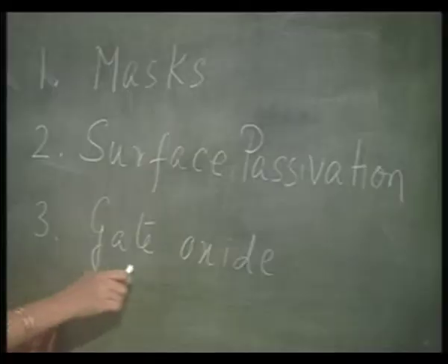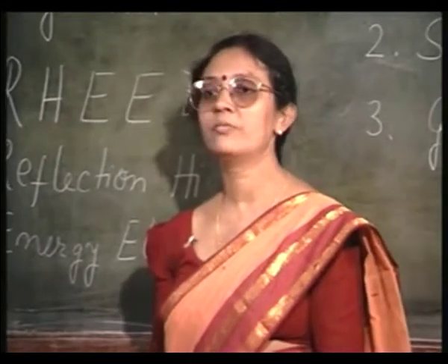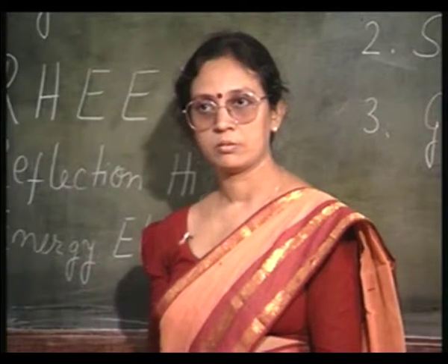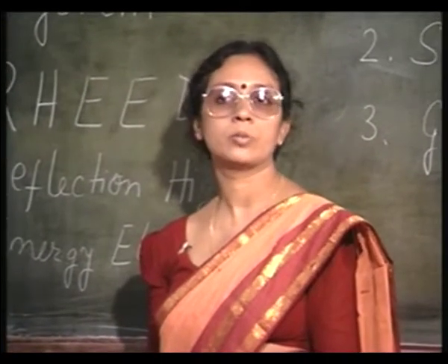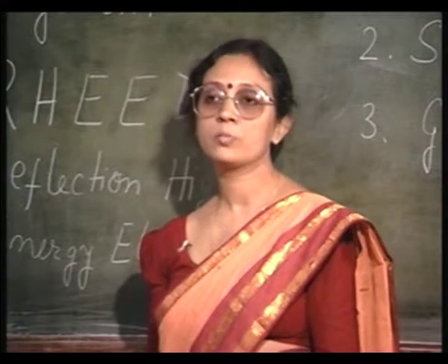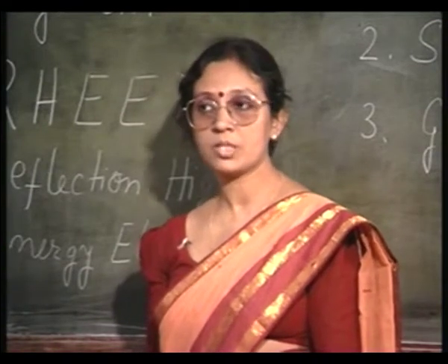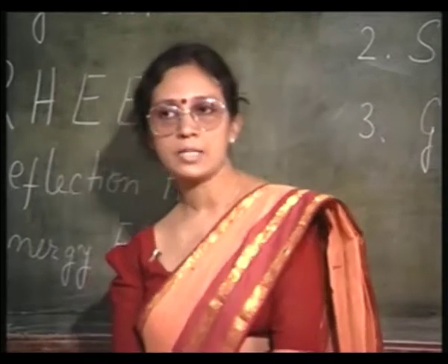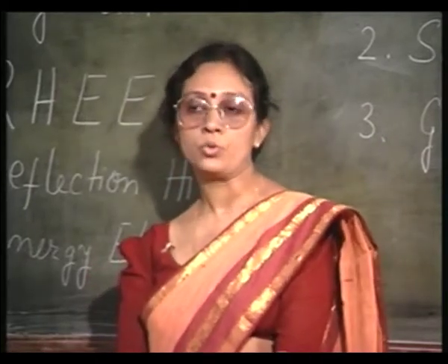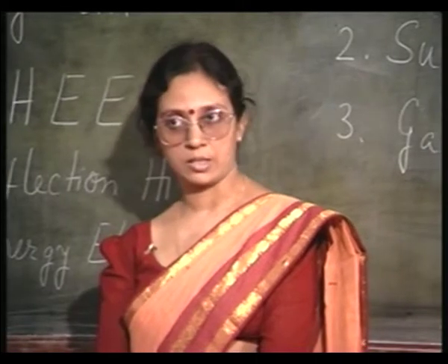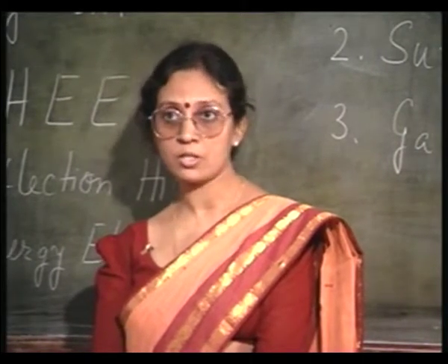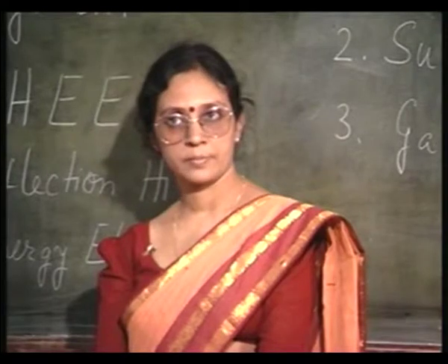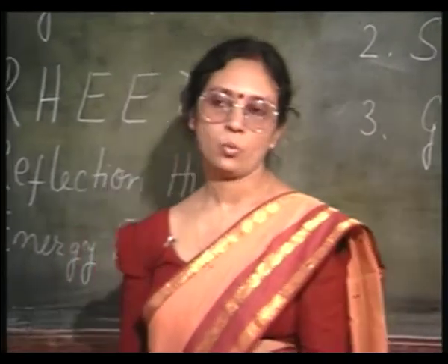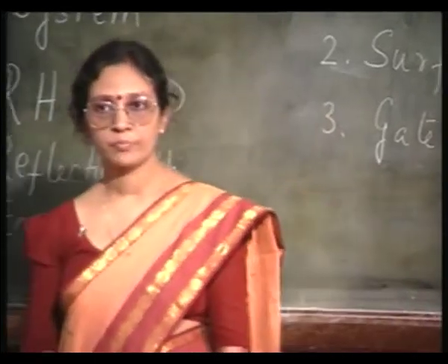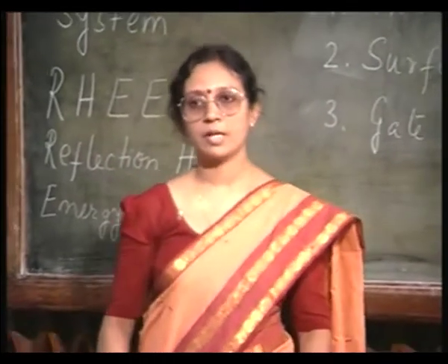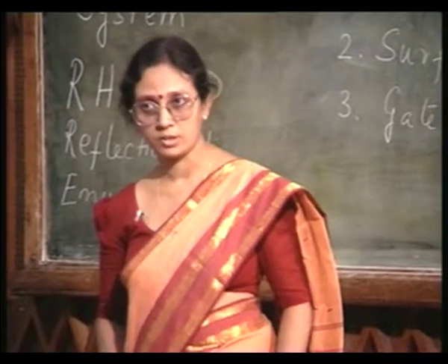You see, for gate oxide, I am talking about thin oxide, but with very good interface quality. For the masks, I am not that bothered about the interface quality. I am bothered more about the thickness. So, depending on these requirements, I will suitably use different oxidation techniques in order to grow thin oxides or to grow thick oxides. But whatever I want to grow, it has to be a chemical reaction between silicon and oxygen.